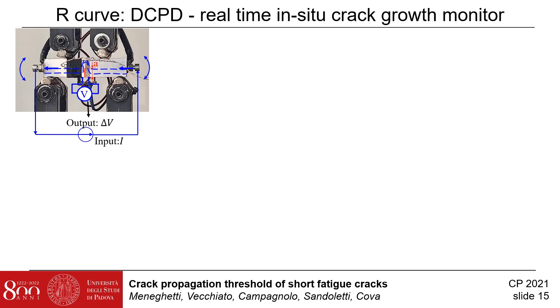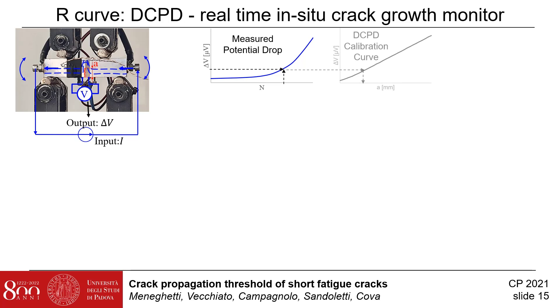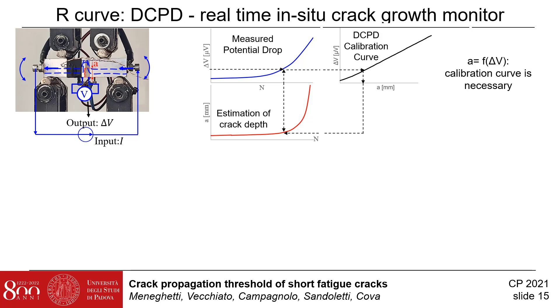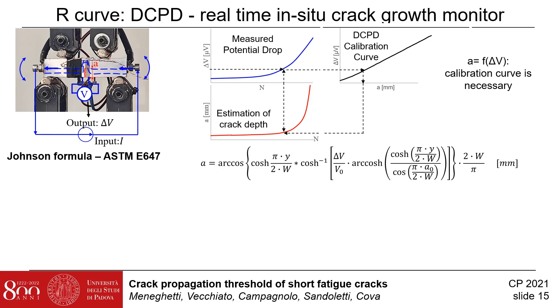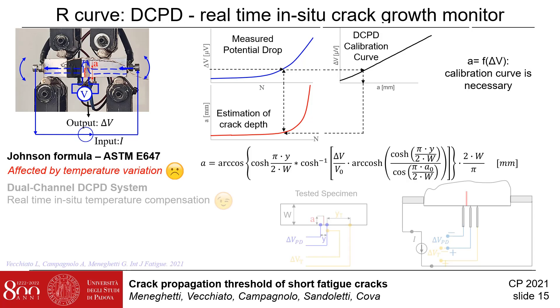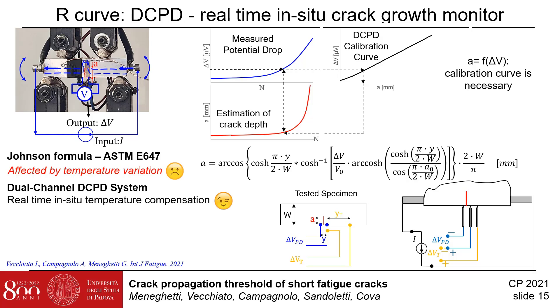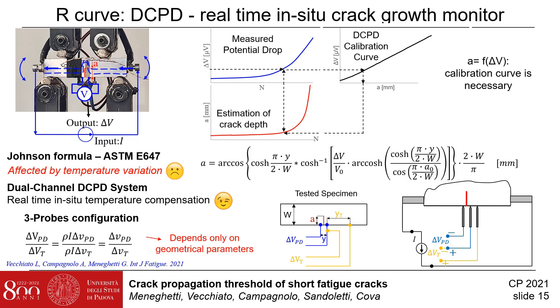In addition, the crack growth has also been monitored by the direct current potential drop technique, which allows measuring the potential drop close to the notch mouth as a function of loading cycles. A calibration curve correlating the potential drop to the length of the propagating crack can be adopted to translate the acquired data in terms of crack length as a function of loading cycles. The Johnson formula is widely adopted in the literature; however, it is well known that it is affected by variations of the material electrical resistivity due to temperature variation. To overcome this issue, a dual-channel DCPD system based on a 3-probes configuration has been adopted. The potential drop active channel data VPD is measured across the crack, while a reference channel data VT is measured between one probe of the active channel and a reference probe located on the same specimen. The ratio delta VPD over delta VT does not depend on resistivity and therefore on temperature.